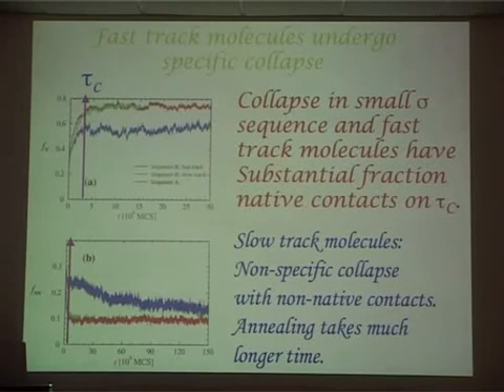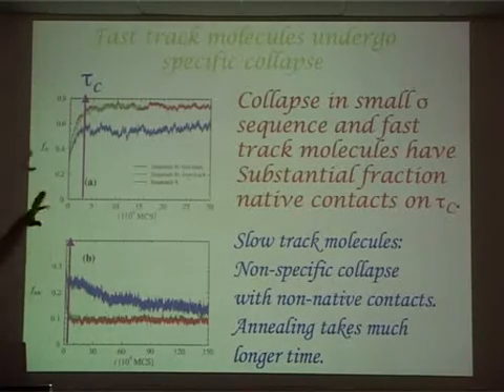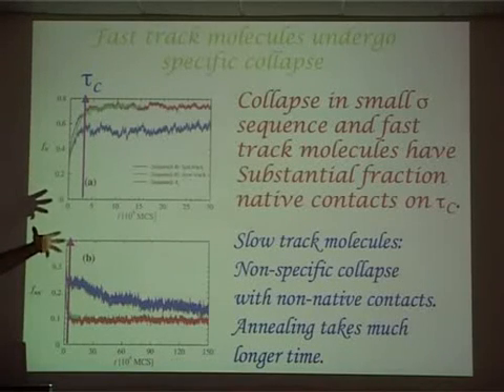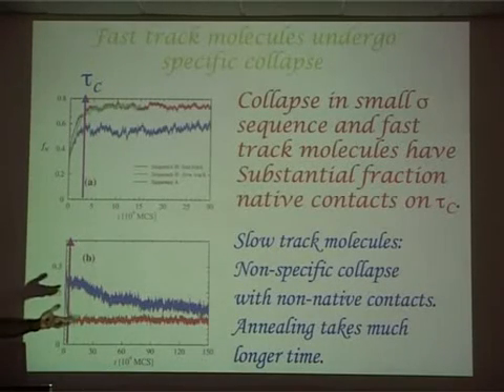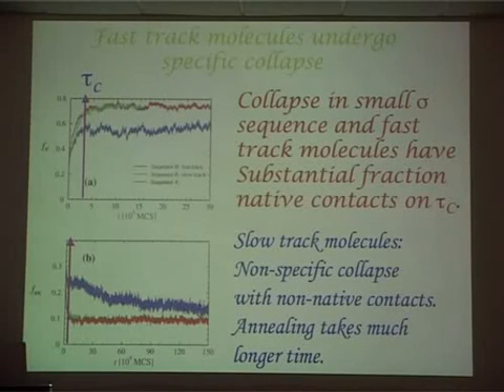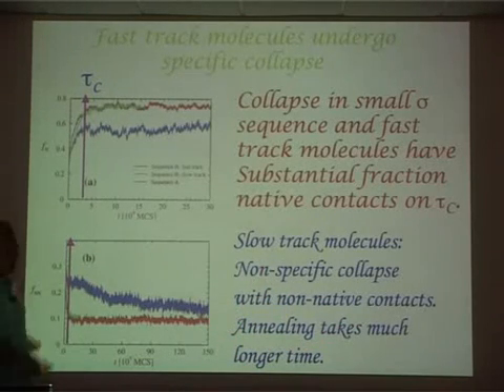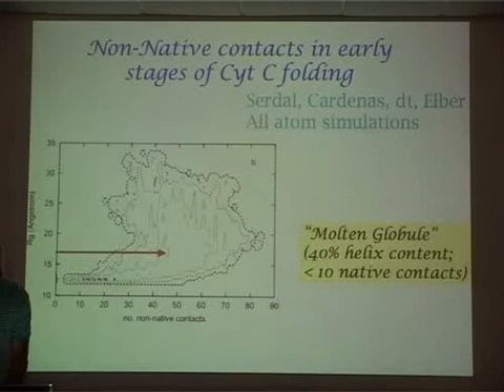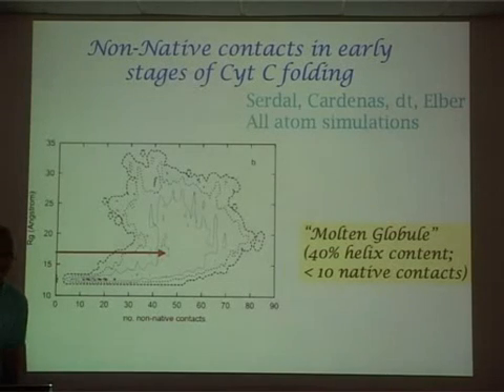In one, it forms largely the specific collapse containing interactions that are already present in the native state, most of them, and in the other case, there is a heterogeneous mix of structures with varying amounts of non-native interactions. This is what we refer to as non-specific collapse, and those defects, if you will, have to anneal, which takes much longer before folding actually occurs. I'm going to stop here. There are lots of experiments coming along, and I may discuss them or I might tell you something else after the break.